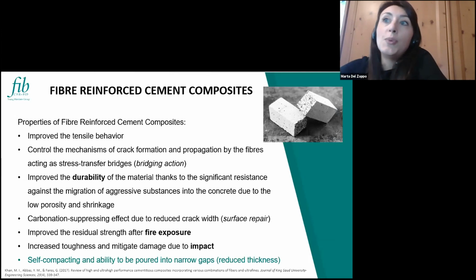So looking at the general properties of such materials, we can say that thanks to the effect of the fibers embedded inside the matrix, we have a high tensile capacity, as we have said before, but we also have high fracture resistance, since the fibers allow us to control the crack formation and propagation inside the material during loading. Then, given the low water to binder ratio, such materials have a very, very low porosity and shrinkage, and so they can ensure a high durability and also carbonation suppressing effects when applied to existing structures.